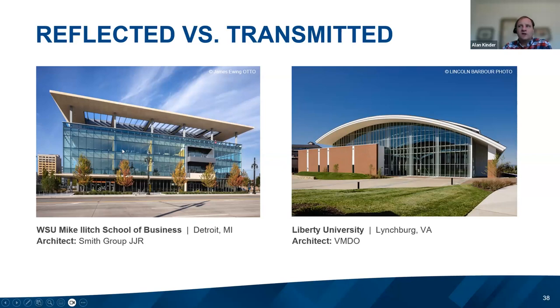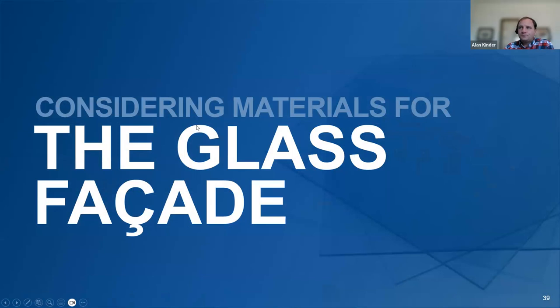So what we start to see is a much greener appearance to the glass, because in transmission, this glass type will be greener. But if we look at the far right, the green color tone is reduced substantially to a more neutral appearance. Reason being, we have a large curtain wall with very deep interior spaces, not a lot of light on the sides or the roof of that structure, so a lot of shadows in the interior. So we're seeing more of the color of light that is reflecting off of that, which is much more neutral in general appearance. So this really is a pretty big extreme, but can highlight just how variable glass can look based off the application alone.